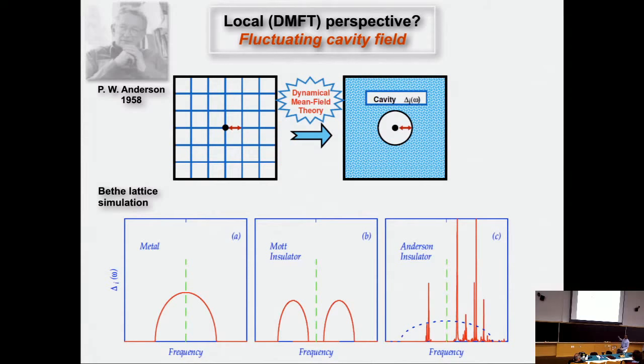But if my neighborhood has bound states, then the local density of states will have just delta function peaks, and maybe at the Fermi energy there will be no state into which you can escape. Okay, and so the local density of states at one particular site, not the average value, but the non-average value, can distinguish not only between a band insulator and a metal, but also between an Anderson insulator and a metal.